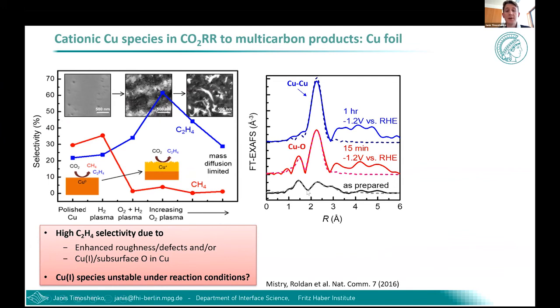In particular, in this study of oxidized copper foils, in the as-prepared state, meaning after treatment with oxygen plasma, Fourier transformed EXAFS spectra show us typical features of oxidized copper. And to some extent, these features are preserved also after exposure to reaction conditions for 15 minutes. So we still see this clear, nice peak corresponding to copper-oxygen bonds. At the same time, there is a growing contribution of metallic copper as seen by this next big feature. After prolonged exposure to reaction conditions, however, no more signature of oxide species can be resolved.